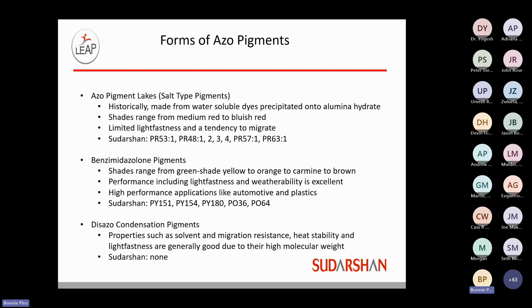The azo pigment lakes, sometimes called salt-type pigments, are historically made from water-soluble dyes; once precipitated with the salt, they become more insoluble than the original dye. From a shade perspective, these are medium red to a blue shade red. They have limited light fastness and tend to migrate some. For Sudarshan, the color indexes are Pigment Red 53-1, the Red 48 series (48-1, 2, 3, and 4), Pigment Red 57-1, and Pigment Red 63-1, all falling into the salt-type category.